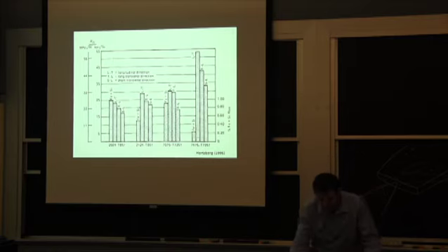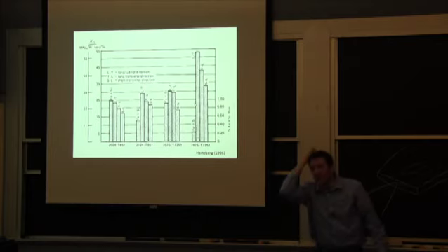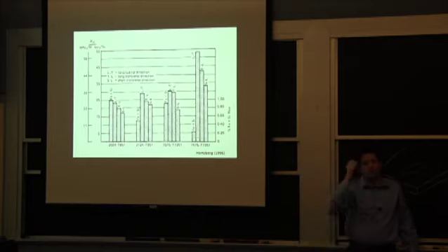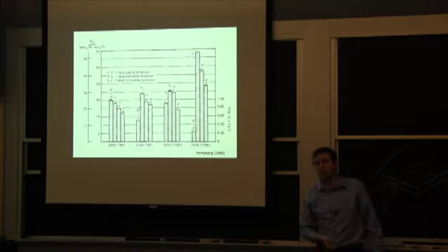So you can see for these two alloys have the same chemistry except the amount of inclusion, and there's a small increase in fracture toughness as a result. But when you get to the 7000 series alloy, the one that's higher strength in general, you can see not that you double, but you increase by more than 60% your fracture toughness just by having fewer inclusions.